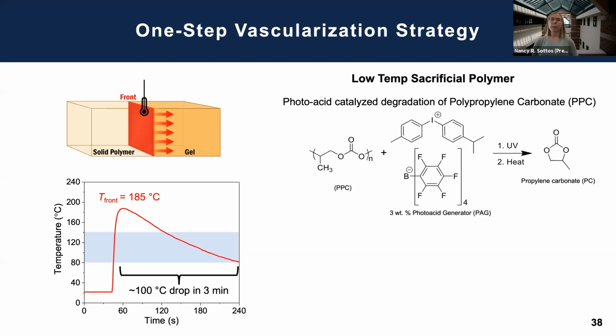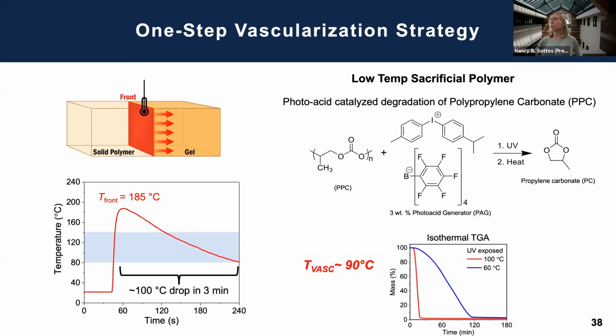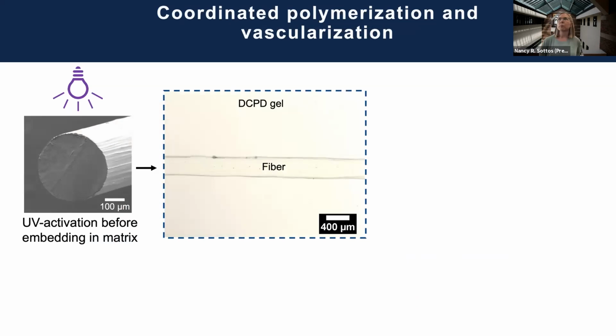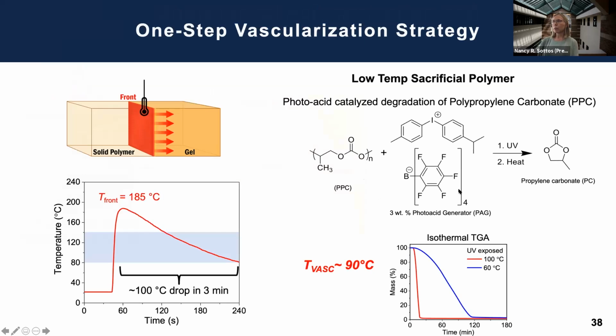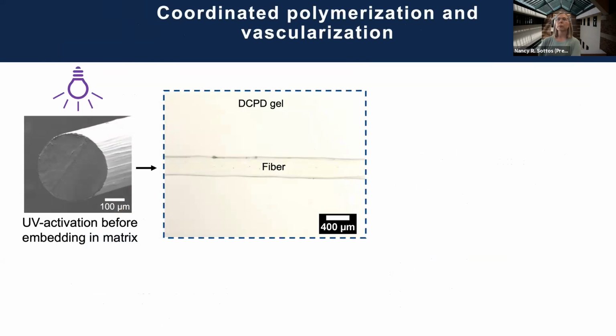The current postdoc and former PhD student Mayank Garg stumbled into this really interesting low temperature sacrificial polymer, polypropylene carbonate, that's been dosed with a photo acid generator, and it is able to degrade at fairly low temperatures. In fact, roughly around 90 degrees C, which was perfect for our application, and it's able to do it fairly rapidly at those temperatures. As this goes, I should mention, it goes from a polymer, PPC, to its monomer, propylene carbonate. And because this is a thermoplastic, it's also very easy to 3D print, as you'll see, and also very useful. But here it's been pulled into fibers.